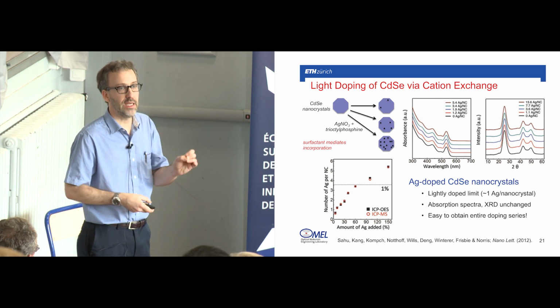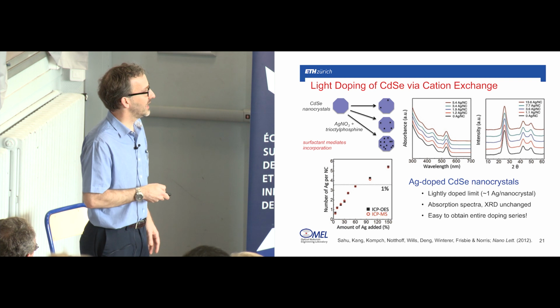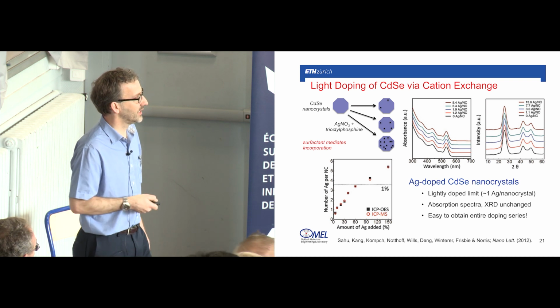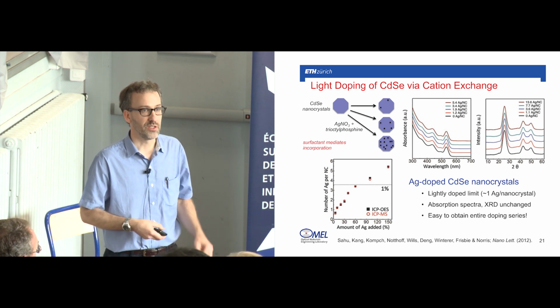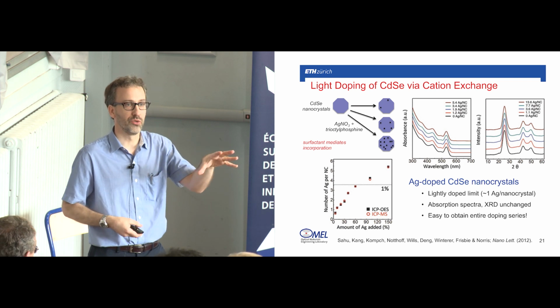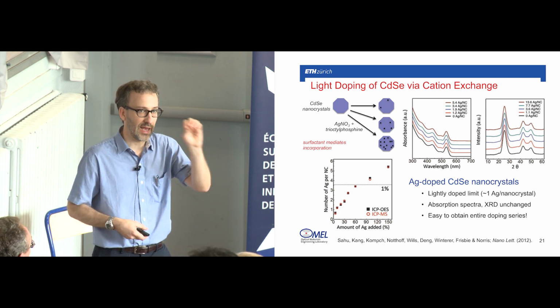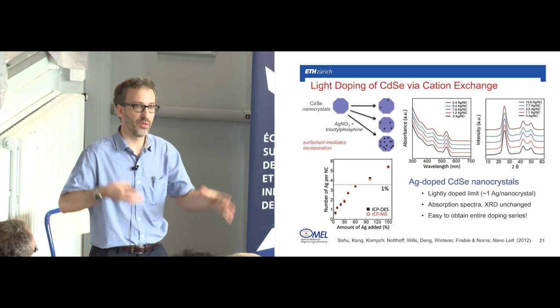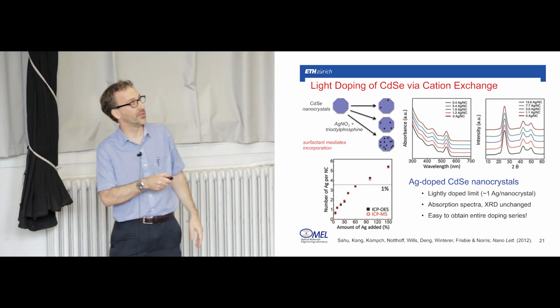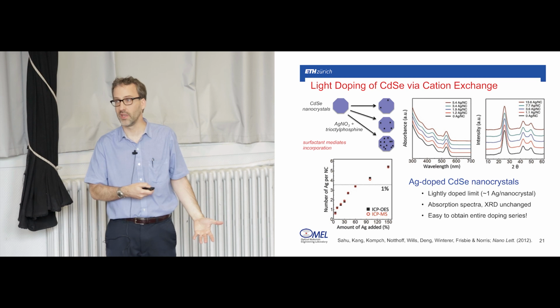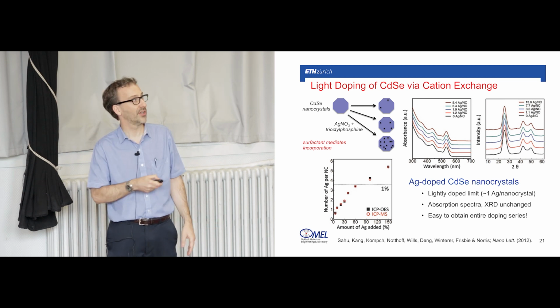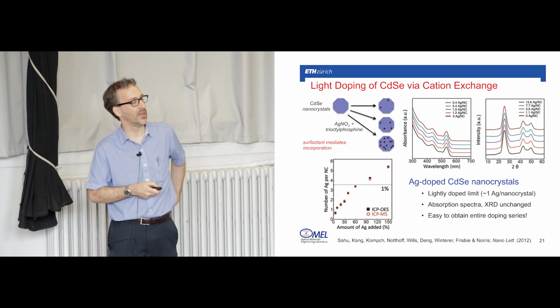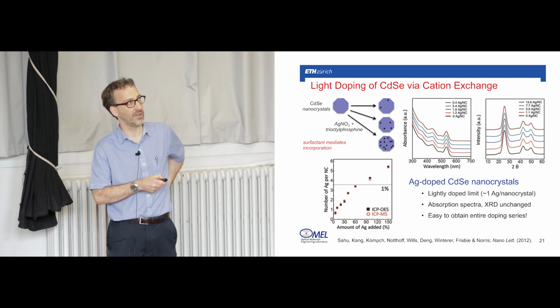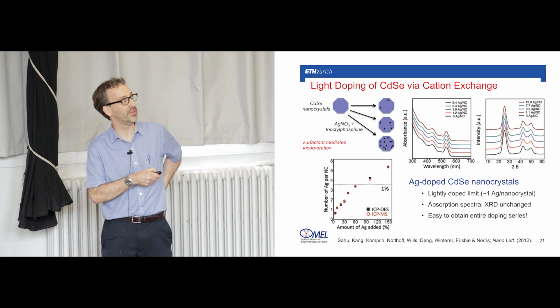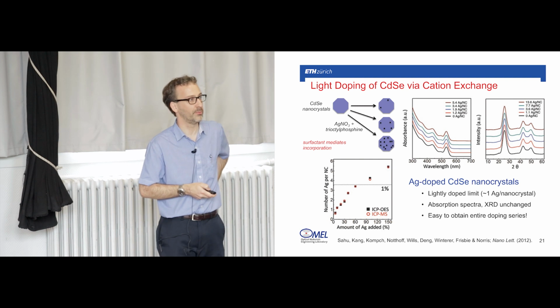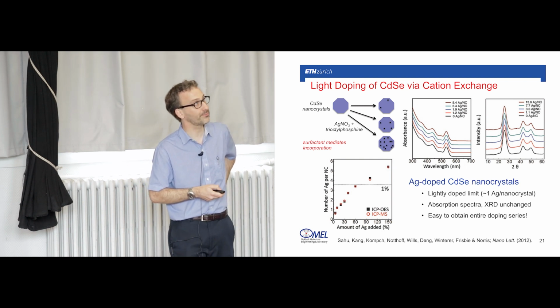But a really key thing about this approach is that it's extremely easy to obtain an entire doping series now. Because if you try to add in some silver while you're growing your cadmium selenide particles, of course you affect the growth and the shape. And so it's very difficult to make a series of samples that are all identical in a typical reaction, but have a different number of dopants. By using cation exchange, it's very easy to do that. You just make a big batch of these, and then you introduce portions of it to different amounts of silver.